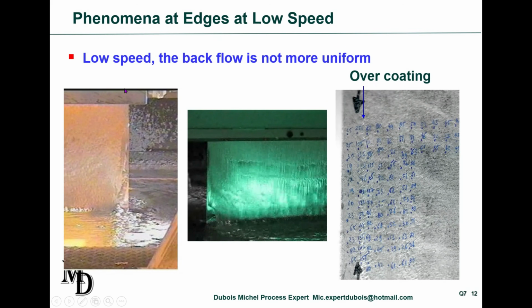But you see, as soon as you are running below 60 meters per minute or 50, the backflow going back to the bar makes this type of oxide. We have a lot of pictures that show what happens. And this induces an overcoating that is not located at the extreme edge.